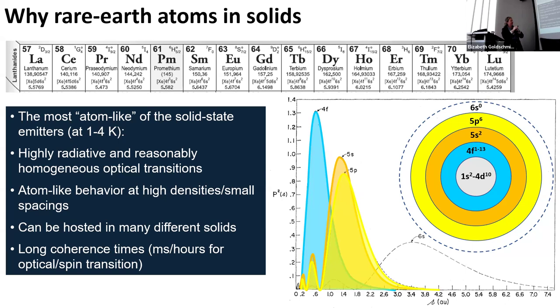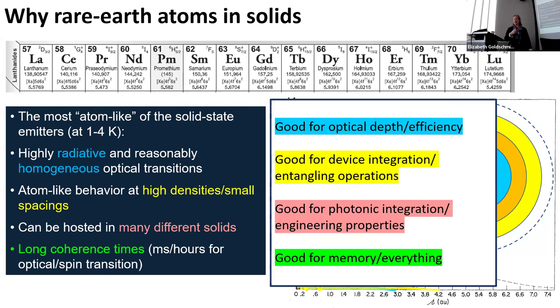Also, I can kind of host them in anything I want, because the host doesn't matter. It's kind of just a weak perturbation on what's going on in there. And then the real reason is I get crazy long coherence times. So spin coherence of 6 hours has been demonstrated in these systems. I can get optical coherence times of several milliseconds in these systems. So for quantum memory, that's really, really good. Why doesn't everyone work on rare earth atoms in solids? First, these things are good. They're good for all the things that I said I wanted on the last slide.